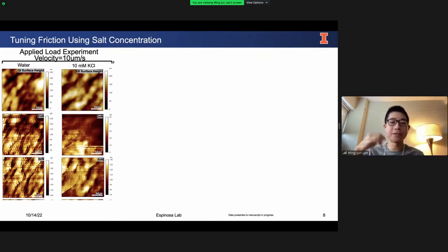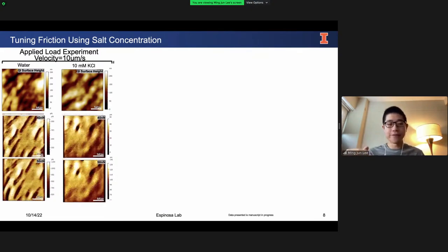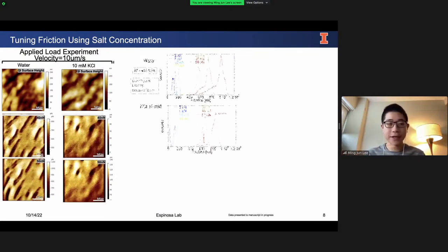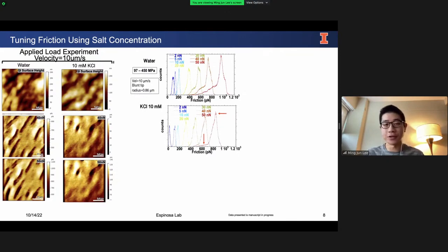And then I apply different forces, different applied loads onto the hydrogel, starting as small as 2 nanonewtons that you see in the middle row, followed by 5 nanonewtons, and then there are some intermediate values, and finally ending in 40 nanonewtons and 50 nanonewtons. For your convenience, I have summarized the friction force values into histograms here. So we have water condition on the first column, corresponding to the first row histogram, and then the salt solution condition, which is the second column of AFM images, corresponding to the second row of histograms.